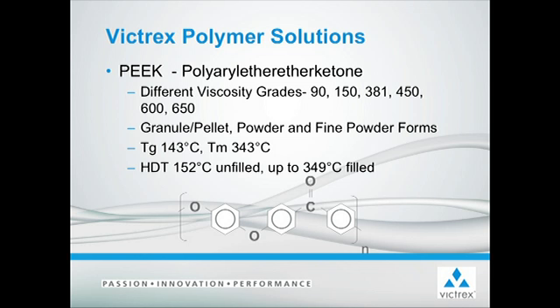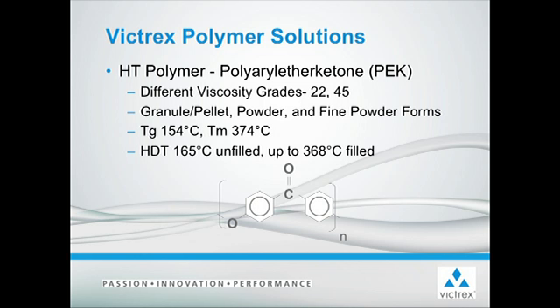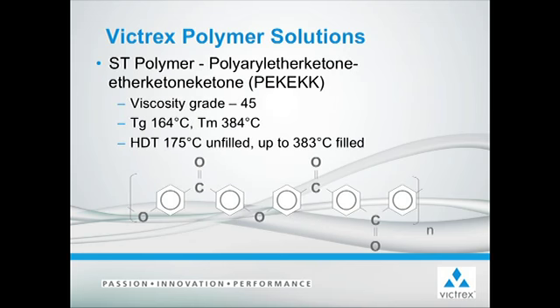These are all available in granule or pellet form, powder or fine powder, and have a glass transition temperature of 143 C and a melt temperature of 343 C, an HDT of 152 C when unfilled, and up to 349 C when filled. Our HT polymer, or polyaryl ether ketone, or PEK, is available in 2 different viscosity grades, granules or pellets, powder and fine powder forms, and has a glass transition temperature of 154 C and a melt temperature of 374 C, an HDT of 165 when unfilled, and up to 368 C when filled with reinforcing materials. Our ST polymer, or polyaryl ether ketone, or PEK-EKK, is available in 1 viscosity grade, has a glass transition temperature of 164 C, a melt temperature of 384 C, an HDT of 175 C when unfilled, and up to 383 C when filled.